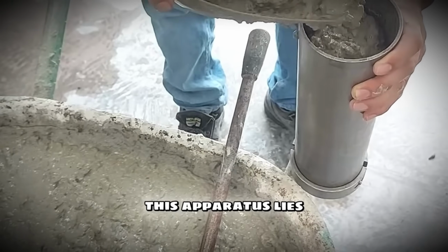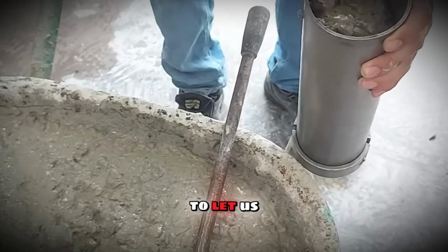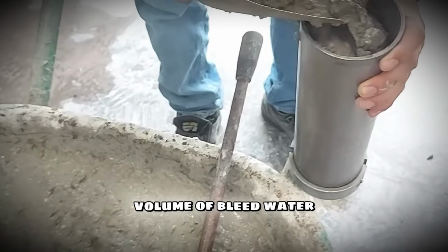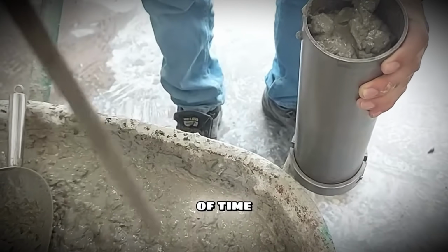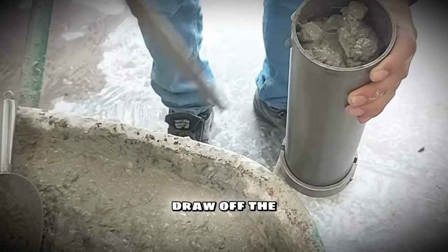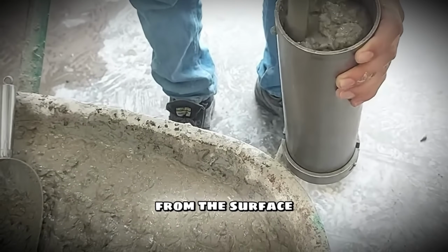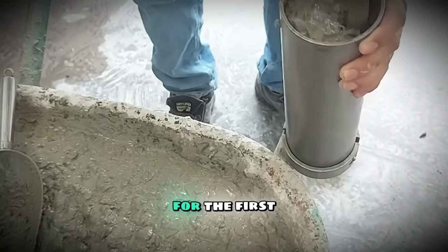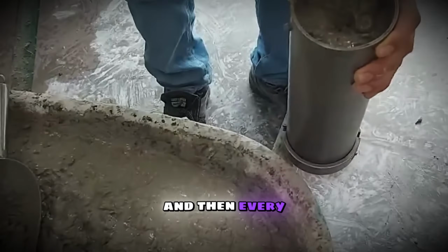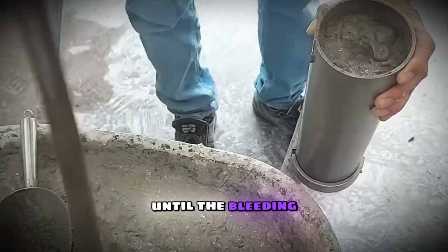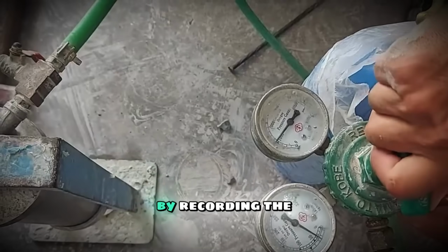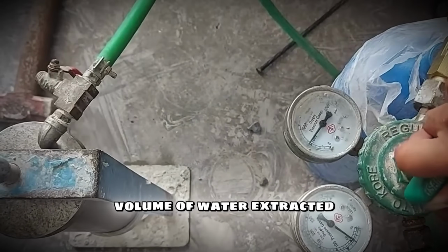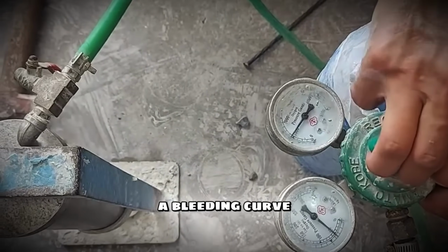The magic of this apparatus lies in its ability to let us precisely measure the volume of bleed water over specific intervals of time. Typically, a technician will draw off the accumulated water from the surface using a pipette every 10 minutes for the first 40 minutes, and then every 30 minutes thereafter, until the bleeding absolutely ceases. By recording the volume of water extracted at these precise intervals, we can plot a bleeding curve.